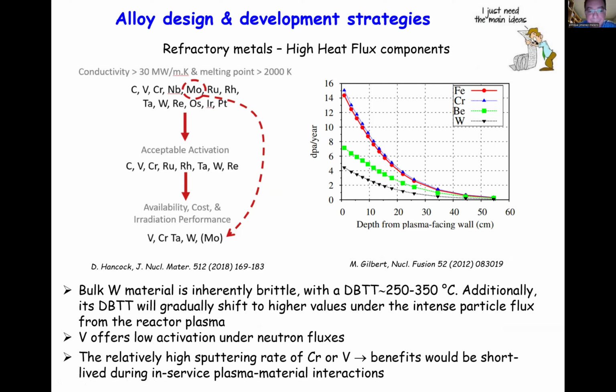So we end up mainly with tungsten, which is also the highest melting point material in the periodic table. Now, tungsten is not the ideal candidate, but it's the one that is currently being developed for plasma-facing components. It's brittle, and the ductile to brittle transition temperature is between 250 and 350 degrees, depending on the microstructure and the processing, but it becomes even more brittle at higher temperatures when it's under radiation in service.